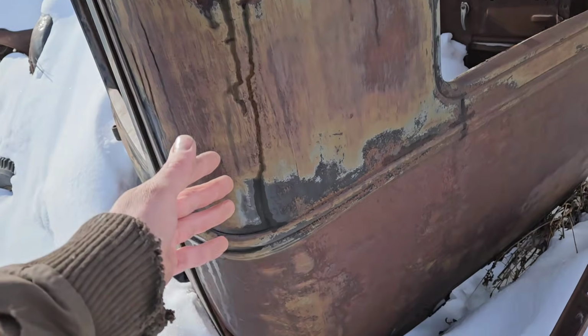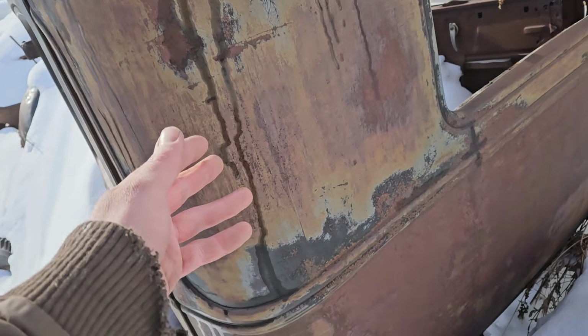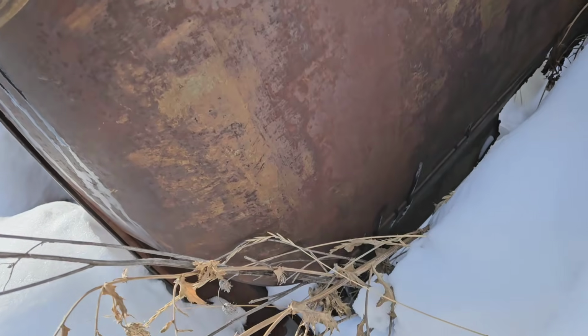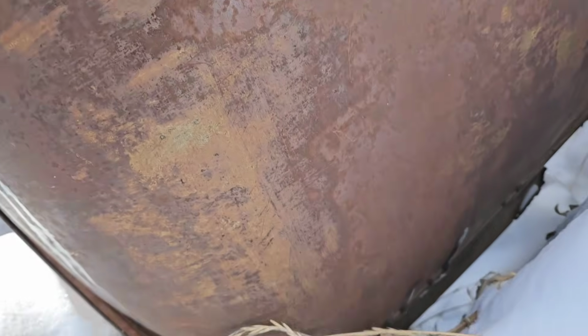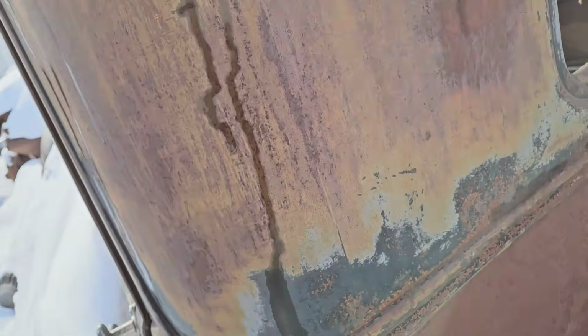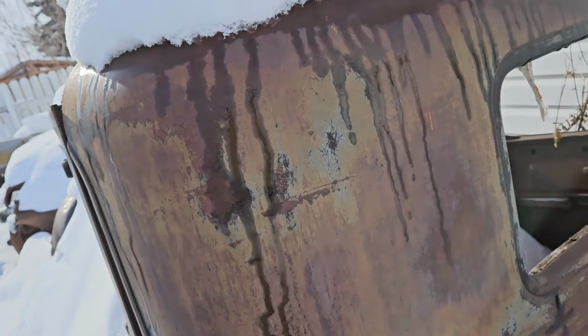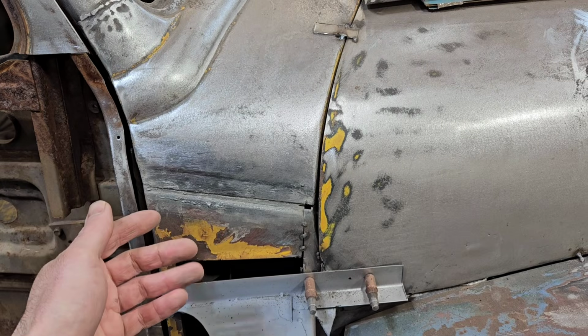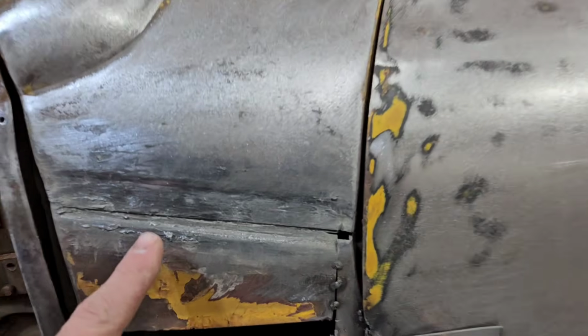Here's how that seam looks on the outside. There's no filler on this, and there's barely any paint left at all, but that seam is still holding up strong after 95 years. Here's what a factory lap weld on an exterior panel looks like with the lead removed.